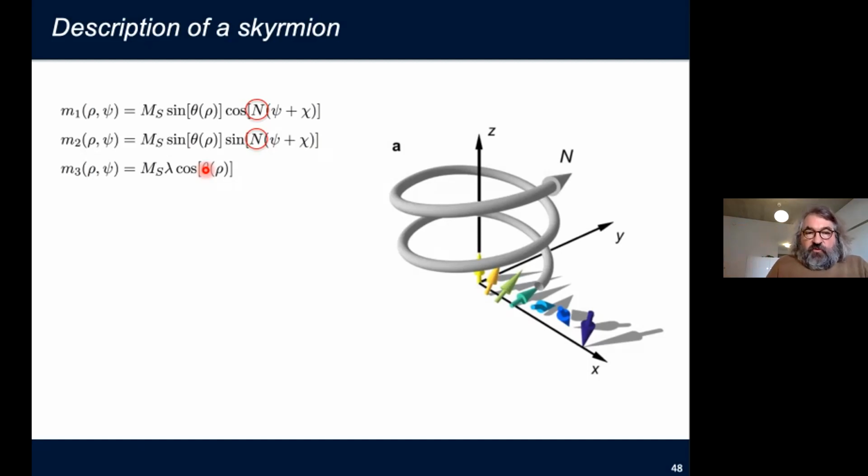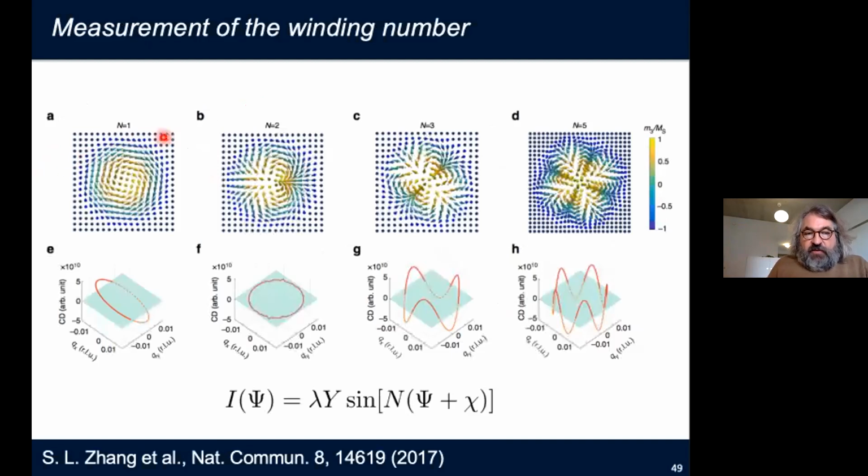So if you think about an N equals 1, so winding number 1 system, where you wrap it exactly once, we can deduce that from the zero crossings of our dichroic intensity, shown here as a pseudo 3D plot. And these are higher order skyrmions, so N equals 2, 3, and 5, etc. This is an N equals 2 system, which looks quite knotted. The way to decipher that is you can think about cuts through the system where your domain wall would have 2 windings essentially in the skyrmion system.